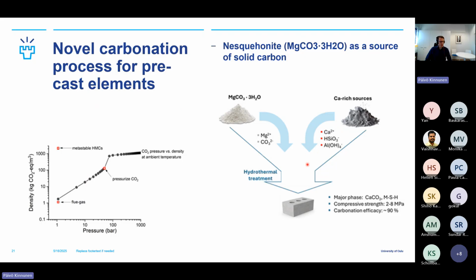And the question that we posed is, can we take this nesquehonite, where we have the carbonate, and combine it with calcium-containing sources without losing the CO2? So where would the CO2 go is one question, and also would we get binder out of that? Our initial guess was that calcium carbonate is more stable, so we hypothesized that it would go to calcium carbonate and stay in the system, and then MSH is also stable, so that would be the binder phase. So that was what we came into this with.